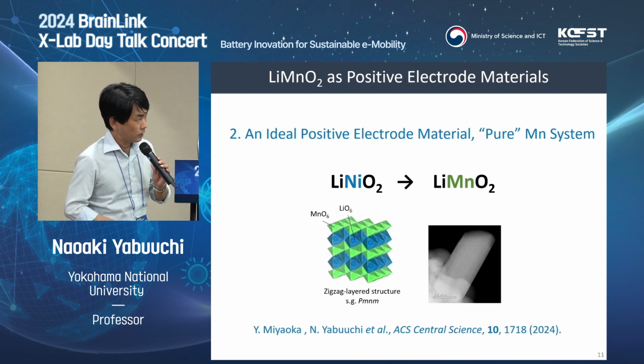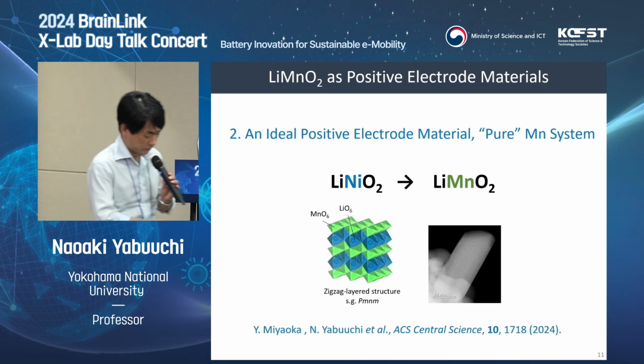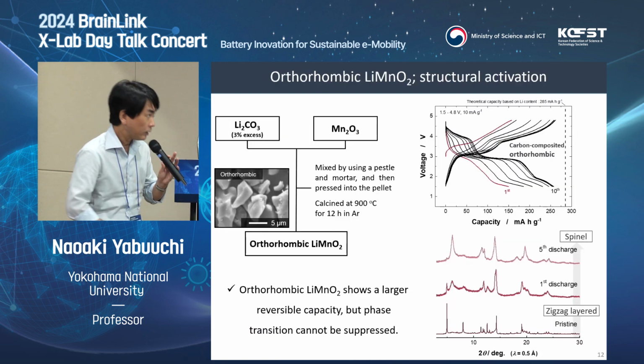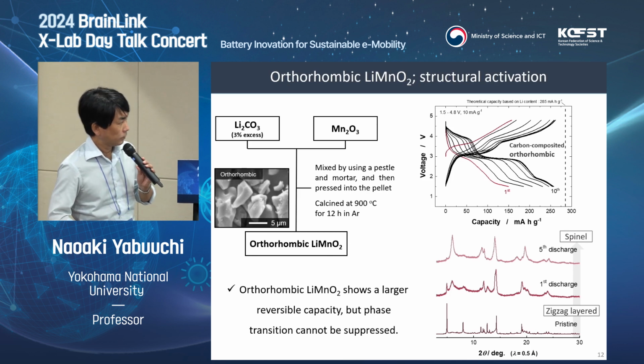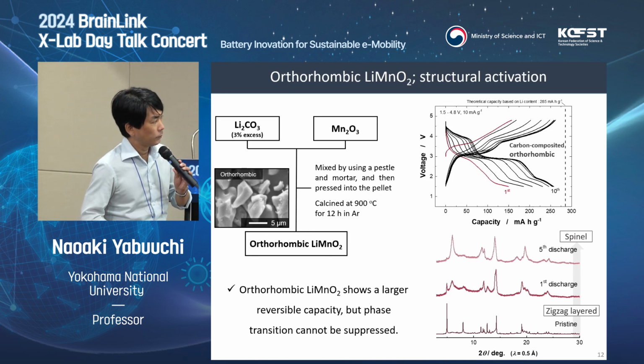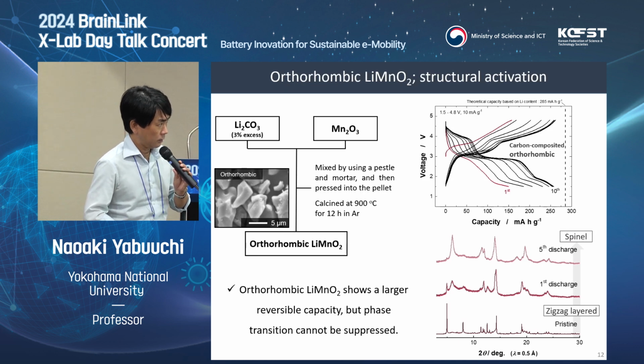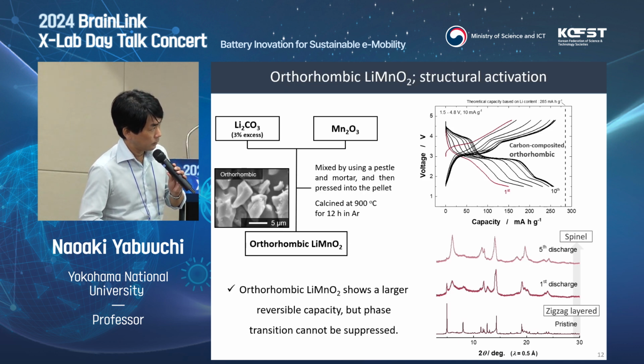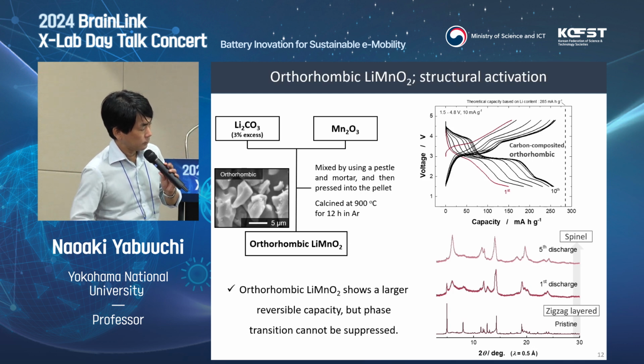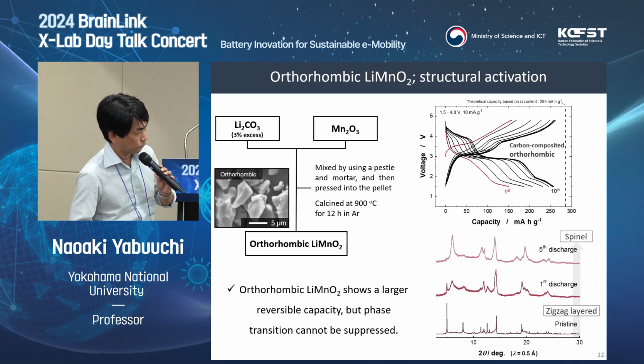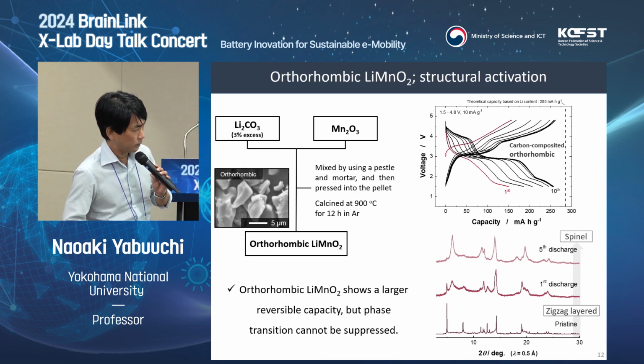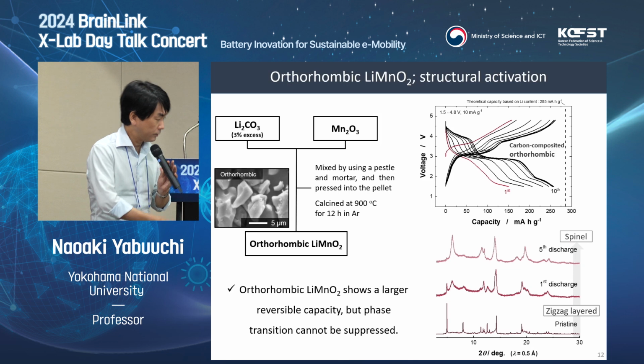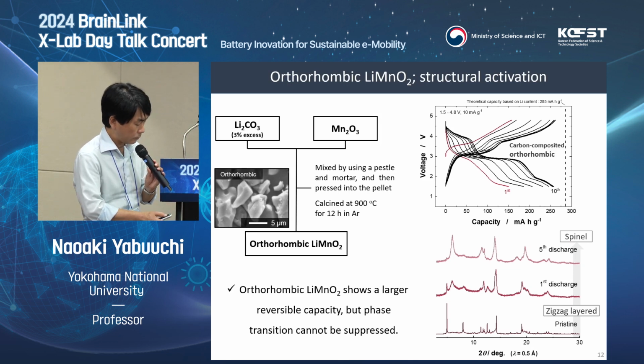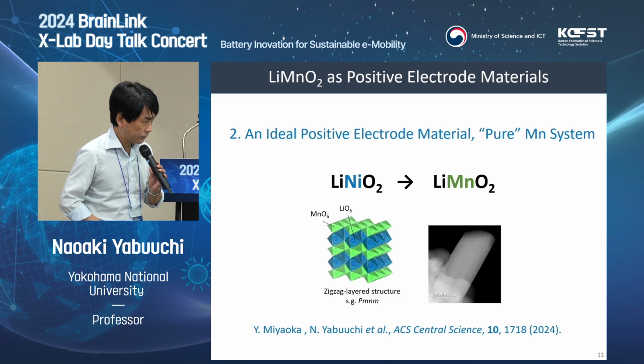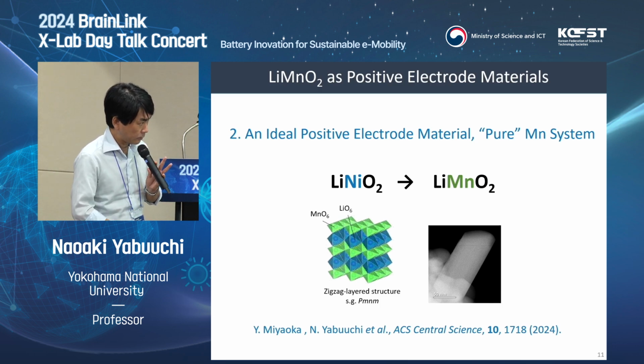The thermodynamically stable phase of lithium manganese O2 is the so-called zigzag type layered structure. However, this sample also has many problems. For stoichiometric lithium manganese O2, the initial discharge capacity is not so high. Upon cycling, you can see an increase in reversible capacity. This is associated with a gradual phase transition into a low crystallinity spinel-like phase. We carefully analyzed the reaction mechanism of lithium manganese O2 with different lithium polymorphs in these publications. So please check our publications in detail.